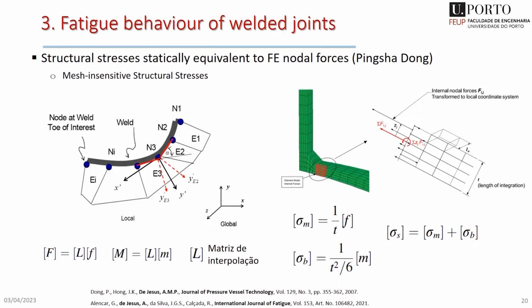Here we are talking about two important aspects, two pictures. First, a structural stress definition, which is stress linearized across the crack propagation path. That stress definition is totally compatible with the nodal forces from numerical simulation. We are not using stresses from the finite element simulations. We are using nodal forces just to get some mesh insensitivity in this process. So structural stress in the end will be the superposition of the membrane and the bending stresses, which is a linearization of the stresses across the crack propagation path.